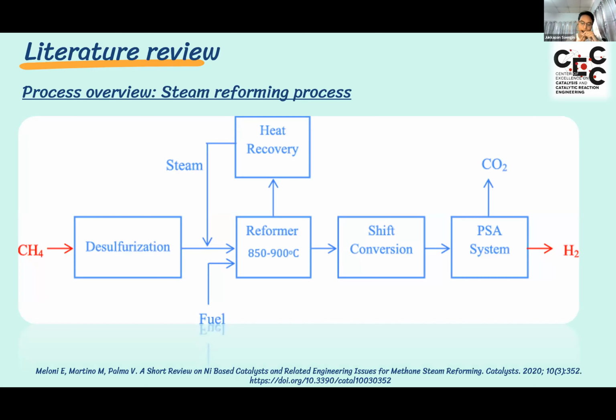And this is a process overview of steam reforming. This is a diagram of steam reforming. It starts with feeding methane into the desulfurization unit to remove sulfur impurities in the methane, and then it reacts with steam which comes from the heat recovery, and fuel is added to generate heat for the reaction. The reaction takes place in the reformer at about 850 to 900 degrees Celsius, and then goes to shift conversion and pressure swing adsorption to separate hydrogen gas and carbon dioxide.